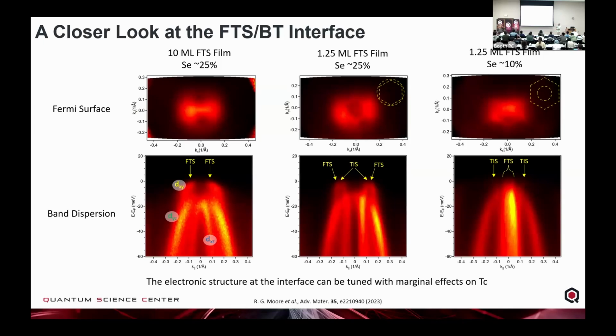but as we zoom into just a single monolayer, because once again, ARPES is a very surface sensitive technique. The light comes in and the electron comes out, but the electron is charged, and so it's very reactive to the things around it. So there is an escape depth to which we can get the electron out without it interacting with something.